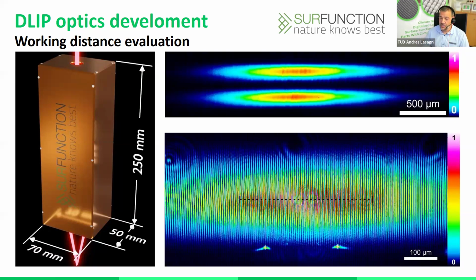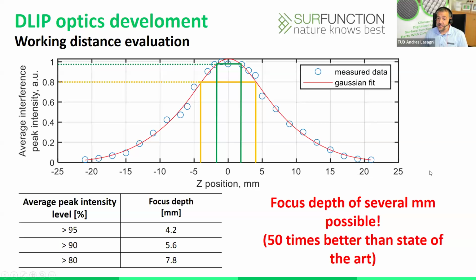That means now we are moving our part following the direction, for example, of the lines, applying laser pulses, and in this way we can produce our periodic structure with, for example, high corrosion resistance, antibacterial properties, a higher biocompatibility, thinking of implants, for example, low friction, and so on. I didn't say that: these images were taken directly from the optical head with a CCD camera so that we can see our interference pattern. And then here there are some calculations.